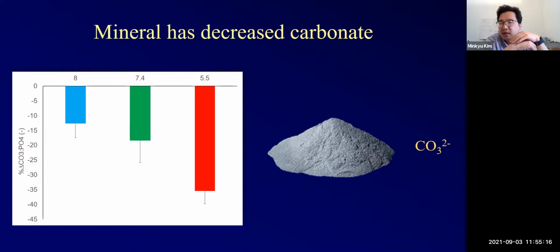And are there any changes in maybe density in the exterior? Yeah, so that's actually another thing we're really interested in. With micro CT, so microcomputed tomography, we did it at a pretty low resolution because we were looking at structure, but we can run it at a higher resolution and run it with phantoms to actually give us density variations. The fact that we see these very dramatic changes in mineral to matrix content on the interior suggests to me that we probably do have a change in density, but I think micro CT will give us that answer. I'm surprised that in Raman we didn't see a change on the outside, but maybe micro CT plus Raman will give us that info. Sounds good.